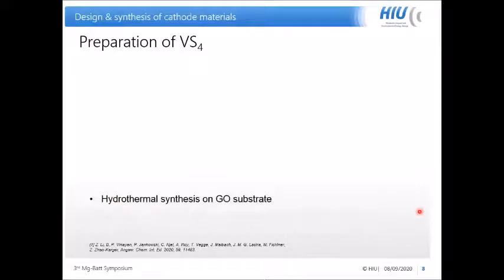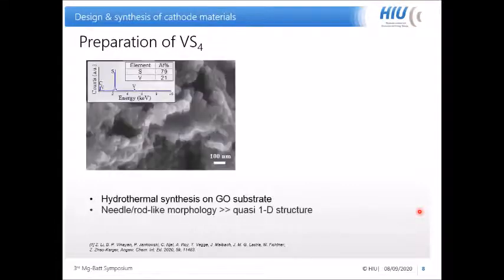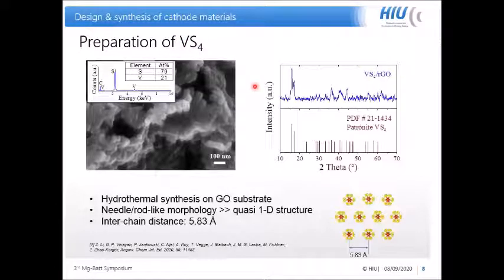To prepare the VS4 cathode, we use a hydrothermal approach and apply graphene oxide as a substrate for the VS4 nucleation. In the SEM image, we see a needle-like structure, which indicates the quasi-1D structure of this material. From the corresponding EDX spectrum, we estimated the atomic ratio between sulfur and vanadium, which is close to 4:1, the stoichiometric ratio of VS4. The XRD pattern also revealed that we have the patronite VS4 structure, and the interlayer chain distance is 5.8 angstrom.